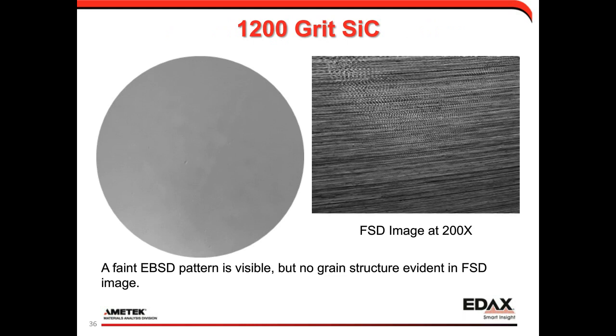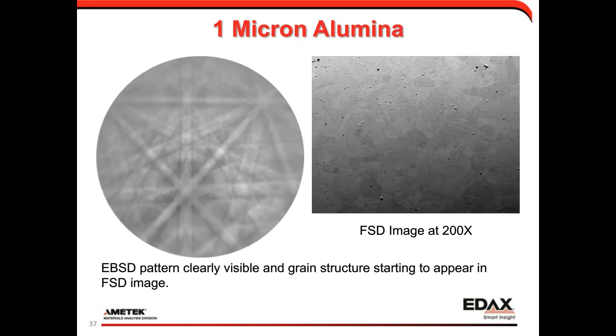So this pattern here on the left, if I convince you to squint a little bit, you'll see there's a very faint EBSD pattern. If we look on the right, the forward scatter detector image, we really don't see much microstructural contrast. We see more the topographic contrast introduced by the polishing. And so, when we're transitioning away from grinding, really we're not at a point where we get much EBSD with just grinding. When we show the results after 10 minutes of 1 micron alumina, now we see an EBSD pattern is very clearly visible on the left. And at the forward scatter detector image, we start to see a little bit of grain contrast within the microstructure.